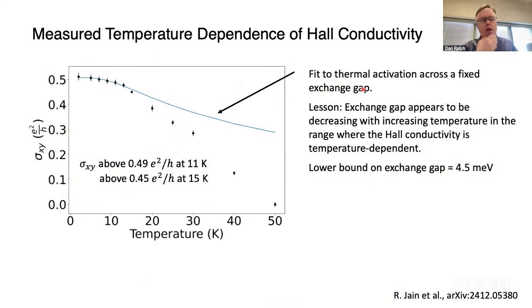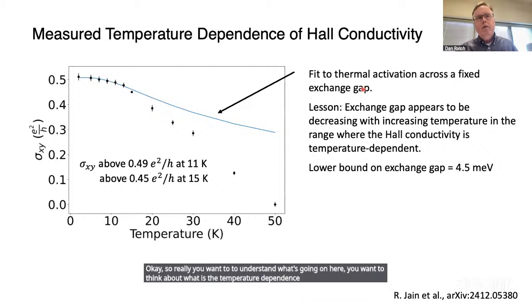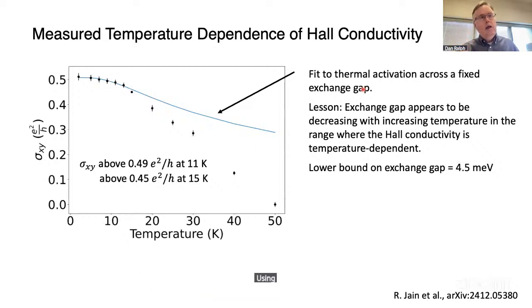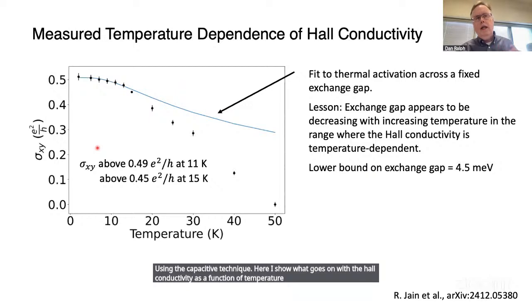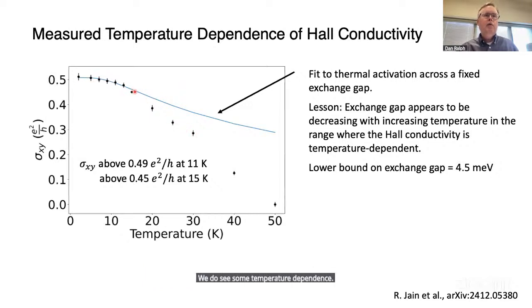Okay, so really you want to understand what's going on in detail here, you want to think about what the temperature dependence is. And it's also possible, as I'll talk about on the next slide, to make direct measurements of the strength of the exchange gap using a capacitive technique. Here I show what goes on with the Hall conductivity as a function of temperature for gating near the middle of the exchange gap. We do see some temperature dependence, but it really kicks in above 10 Kelvin or so.